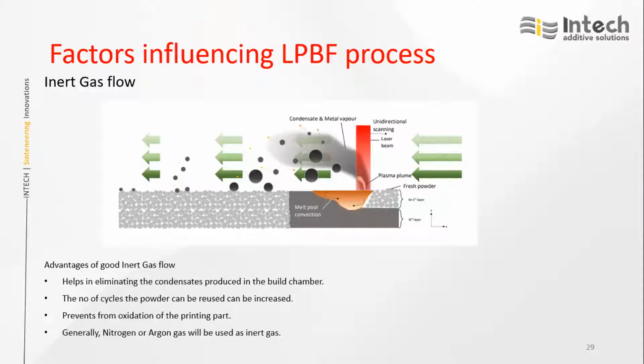All this forms condensate, which, as you can see, falls back on the powder bed as black particles. If this is not removed properly, the powder will get contaminated, and the life period of the powder will get reduced. If it is properly removed with the help of inert gas, then the quality of the powder will remain for a long time and it can be used for many builds. Typically, nitrogen or argon gas is used as the inert gas.